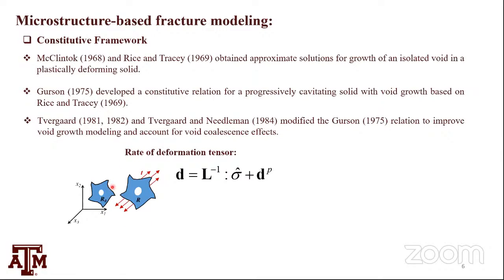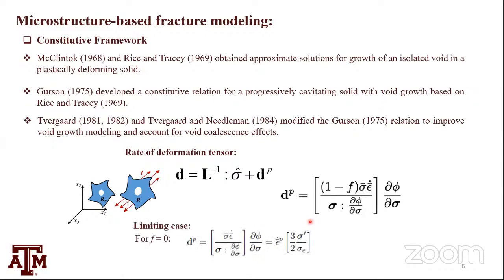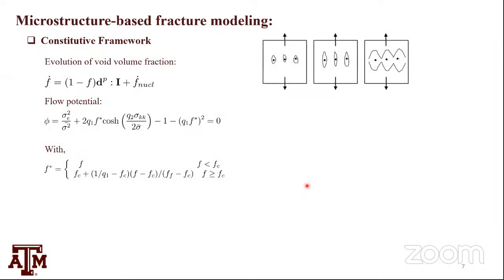Basic, simple idea. We have a material, a pore in it, and we apply a boundary value traction or displacement, and we divide the deformation in two parts, elastic and plastic, not a big deal. We're going to modify the plastic part to account for this variable f, which is the porosity or void volume fraction coming from nucleation, growth, and coalescence. This could also be pre-existing in a material. And phi is my flow potential, sigma is the Mises effective stress, and epsilon bar dot is the effective plastic strain rate. If f goes to 0, dP reduces down to the plastic strain rate in a simple isotropic von Mises material. All right, how does the void evolve?